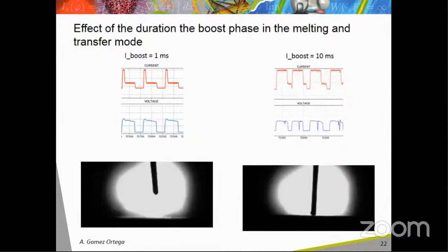Here are two video recordings showing the effect of the pulse duration. The first video shows the wire tip evolution for a short pulse time of 1 millisecond. One can see the formation of a small drop at the wire tip that stays on the wire tip up to the short circuit. The second video shows the wire tip for a long pulse duration of 10 milliseconds.